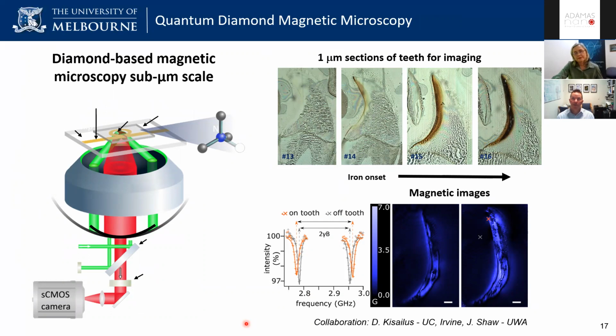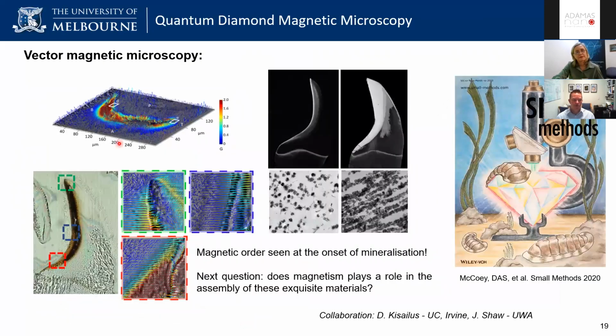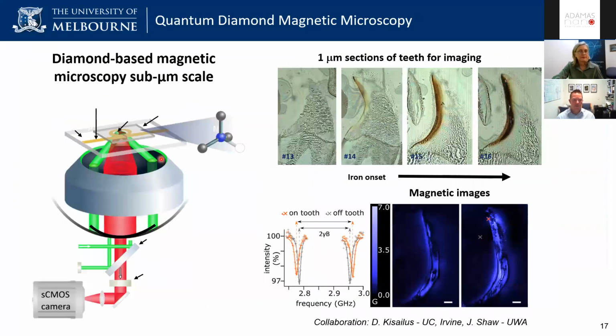Yes, you can. The challenge with nanodiamond is this. When we do vector magnetometry, you can do it in two different ways. You can either align a background magnetic field along each NV axis, and then report the ODMR along that NV axis, then change to the next one and look at the magnetic field projection along that axis, and then combine that information to convert it into a vector magnetic field. That's what we did in this particular case, because that maximizes your sensitivity, if you like, when you can align to a particular axis.